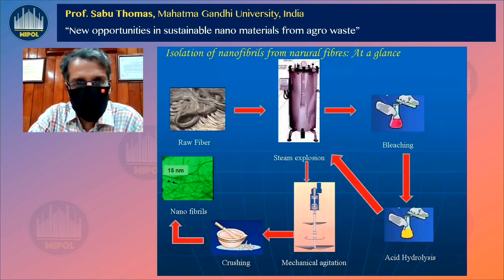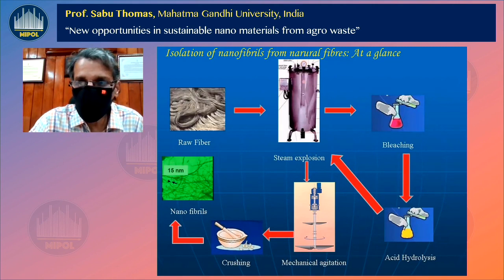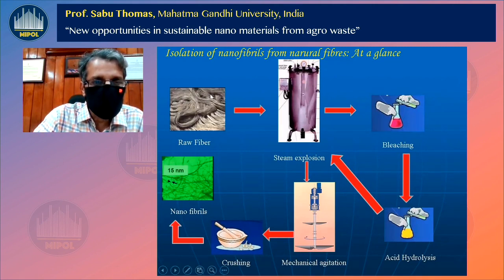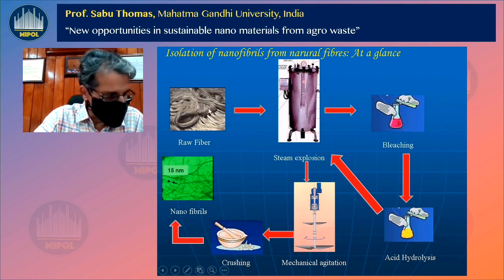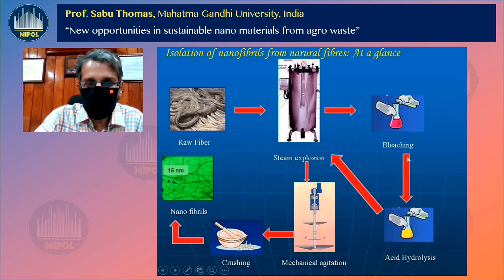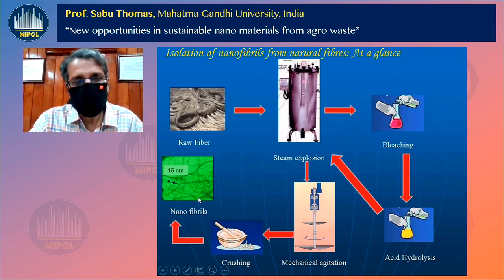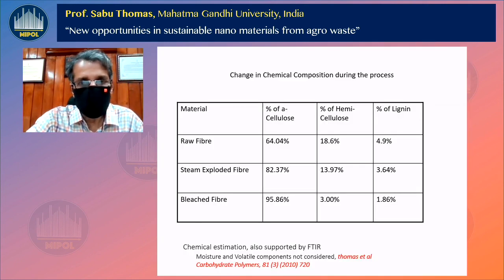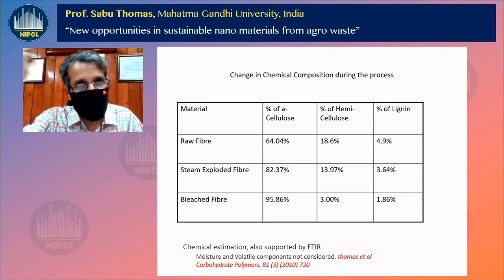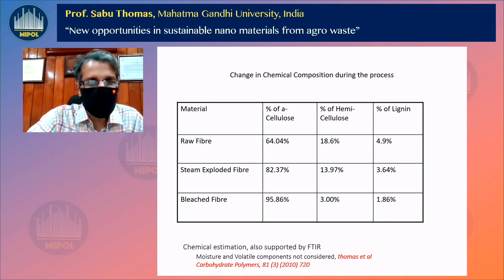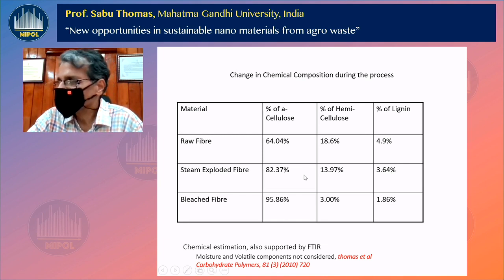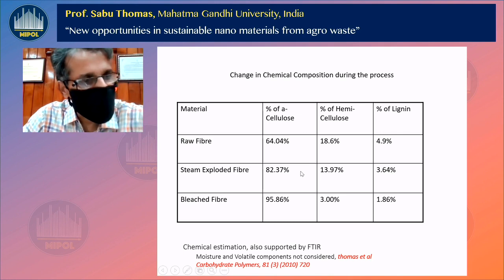Now let me show you what I do in my laboratory. My PhD students collect agricultural waste. It could be sisal or pineapple. We remove all the other material and get the fiber, chop it into smaller lengths, and subject it to steam explosion, bleaching, and acid hydrolysis. Finally, we get beautiful nanofibers. I wanted to show you the dynamics of the enrichment process. The raw fiber has a cellulose content of 64%.